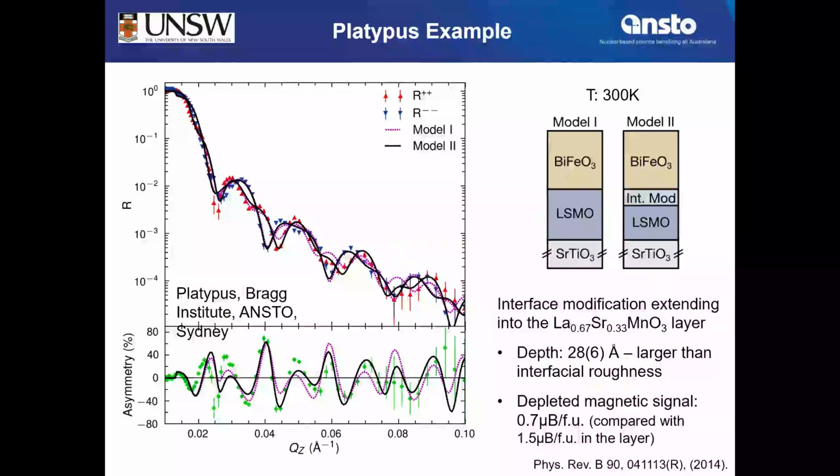So again, neutron reflection is ideal to determine properties of thin films, not only the chemical composition, but also, let's say, surface roughness, or if there's some chemical interpenetration. Perfect, ideal technique. And now, if we use, as shown here, spin up spin flipper position, or spin down spin flipper position, we can see the magnetic structure in the film. So that's an example from my own research.